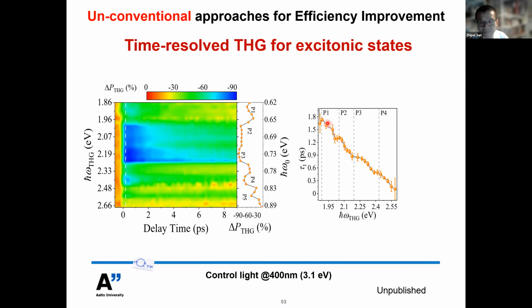If you look at the time response, you can clearly see that when we incident the light at 400 nanometer onto the MoS2, we can clearly see how the carriers relax from a very high energy state to a very low energy state. So this is something extremely interesting.